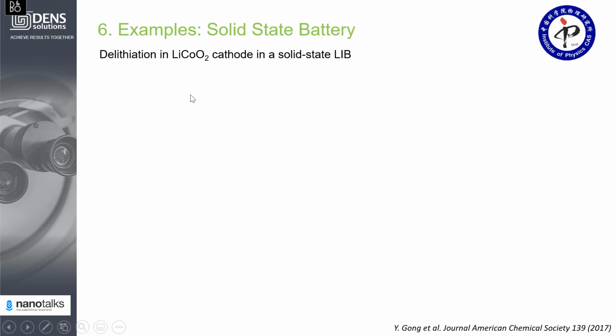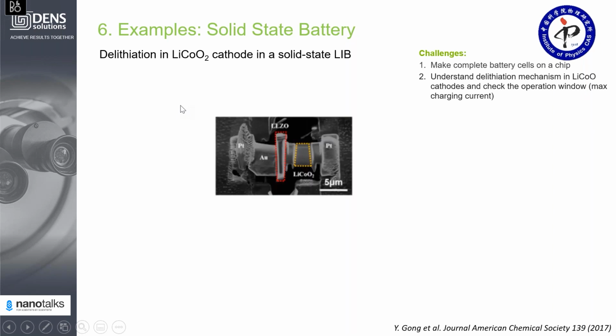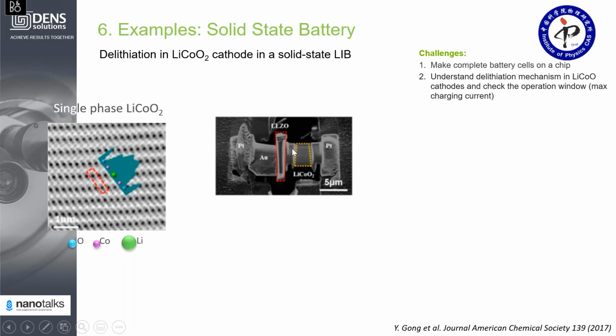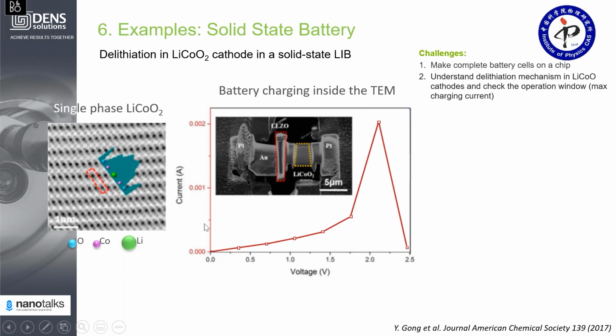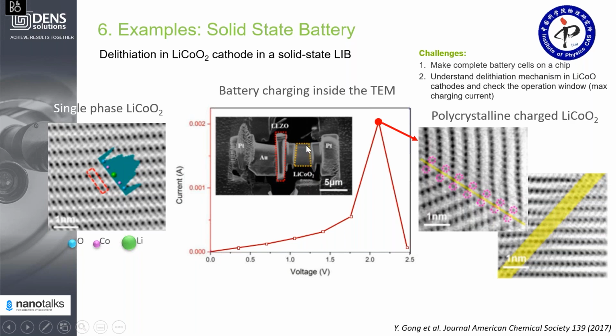The final example is about a solid-state battery. First of all, it's very challenging to make a solid-state battery on the nanochip. Researchers, again from Beijing University, were able to prepare it on the biasing nanochip. The process is very difficult and time-consuming, but it is possible. Here you have the full stack: one electrode, the electrolyte, the lithium cobalt oxide electrode, and also welding points to the chip biasing electrodes. Researchers were able to characterize the cathode material in the as-prepared state. They were able to delithiate the lithium cobalt oxide, see the IV curve, and also observe what happens to the structure when you remove lithium from it. The structure transformed from a single phase to a polycrystalline phase with a certain orientation of those crystallites.